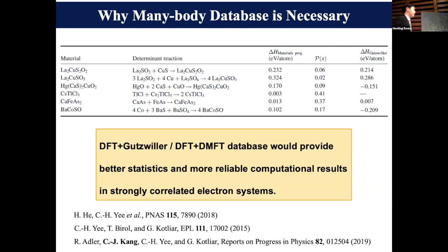Yeah, it's a good question. Our strategy is that scanning the whole chemical reaction space by DMFT is very time consuming. So our basic idea is to scan all possible chemical reactions by DFT at first, and we assume that the chemical reaction doesn't change depending on which method we use. Then after we find the chemical reaction, we compute the DMFT formation energy again, and we found that the DMFT formation energy gives a reliable result compared to the experimental data.